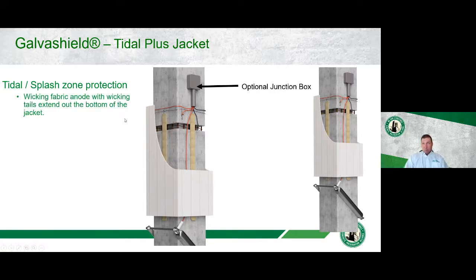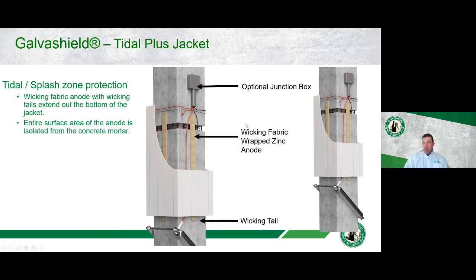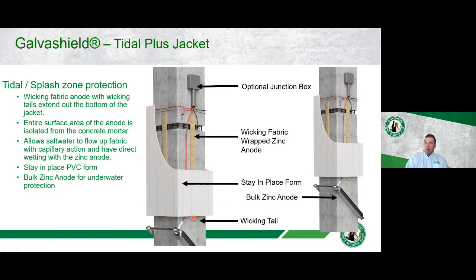So the way that the system components function is we have our anodes that are attached to our pile. They're bulk zinc anodes that are essentially attached to our pile, but they're encased in a wicking fabric. And you'll note at the bottom, this wicking fabric tail extends out the bottom of the jacket. And so this wicking tail at the bottom allows salt water in the bottom of the form and allows the salt water to wick all the way up this fabric and encase and make sure that this entire anode that we have in here is encased or surrounded with seawater, so that this anode will always remain in an active state.